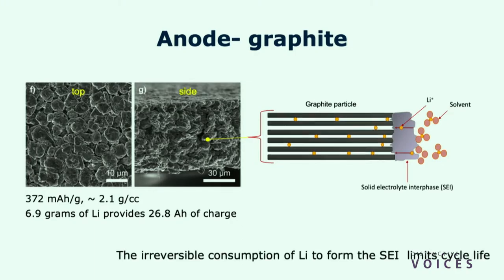Okay, and then one other thing, I thought I'd mention the highlights of lithium ion. What is it that degrades in a lithium-ion battery when we charge and discharge it? It has to do with this rust-like layer called the solid electrolyte interphase. It's like an organic, inorganic layer. Every time a lithium-ion battery is charged and discharged, as the lithium ions go in between these basal planes of graphite, they expand and contract. As they do, small fissures or cracks occur in the solid electrolyte interphase, exposing new graphite, and then it has to reform this rust layer. Every time that rust layer has to reform, it irreversibly sequesters lithium, and that causes irreversible loss. And that's what causes degradation in capacity fade in lithium-ion batteries.